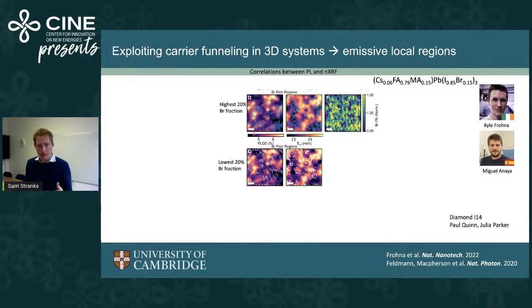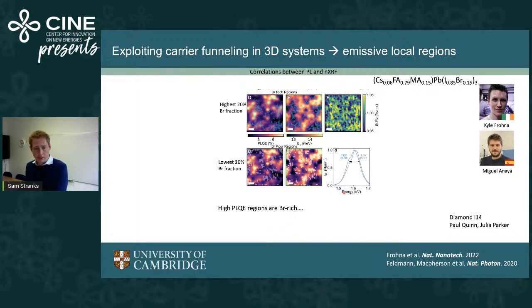In fact, and this is bromine rich with respect to iodine, or the total halide, when we look at the lowest 20% bromide fraction, you can see that it tracks with the low luminescence quantum efficiency. So these results are telling us that the high PLQE regions, where it's very luminescent, are bromine rich. But this is apparently contradictory, because when we look at the luminescence spectrum of these high PL quantum efficiency regions, they're actually slightly lower in energy, and this would be more consistent with an iodine-rich site rather than a bromine-rich site.